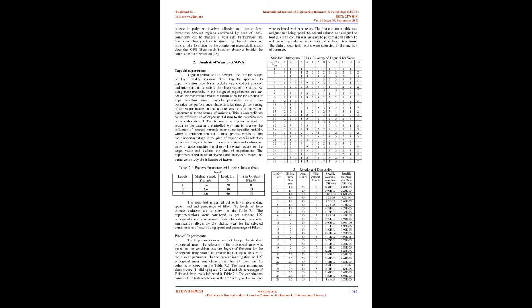The wear parameters chosen were 1. Sliding speed, 2. Load, and 3. Percentage of filler, and their levels are indicated in Table 7.1. The experiments consist of 27 tests, each row in the L27 orthogonal array, and were assigned with parameters. The first column in the table was assigned to sliding speed, S, the second column was assigned to load, L, the fifth column was assigned to percentage of filler, F, and the remaining columns were assigned to their interactions. The sliding wear test results were subjected to the analysis of variance.